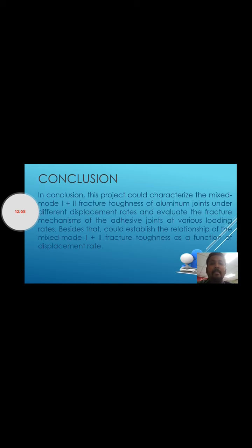Okay, these are the results we got from the end of the test. The conclusion: this project could characterize the mixed mode 1+2 fracture toughness of aluminium joints under different displacement rates and evaluate the fracture mechanism of the adhesive joint at various loading rates. Besides that, it could establish the relationship of the mixed mode 1+2 fracture toughness as a function of displacement rate.